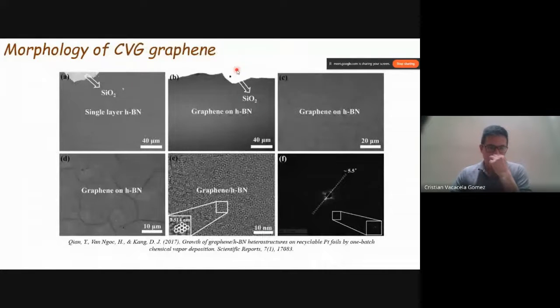In the last one, for example, for CVD graphene, we can see in pictures A, B, C, and D how people, for example, grow graphene on hexagonal boron nitride. So now in this high resolution TEM image, the authors show us a perfect graphene structure with these hexagons. Look at here. We can clearly observe the hexagons created on this single layer graphene sample on hexagonal boron nitride. These are several images, but it's a little difficult to identify all the complete properties.